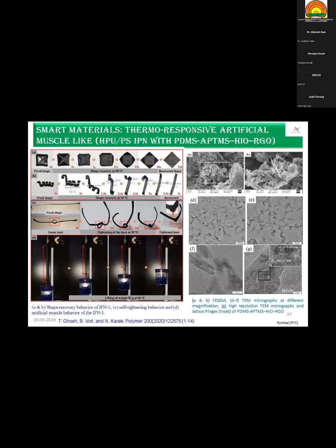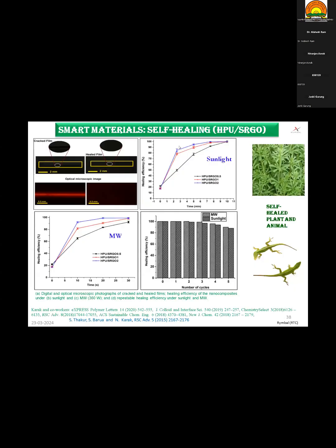One of these is a nanocomposite of castor oil-based hyperbranched polyurethane with an iron oxide and reduced graphene oxide combination, a nanohybrid system, which not only shows fast recovery of the shape fixity, it can even form a knot by itself in 35 seconds, and most significantly, it can lift more than 1,000 times its own weight by using this shape memory system. Thus it can be used as an artificial soft robotic artificial muscle.